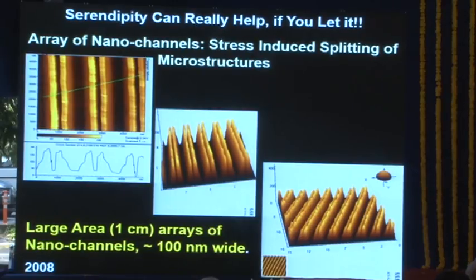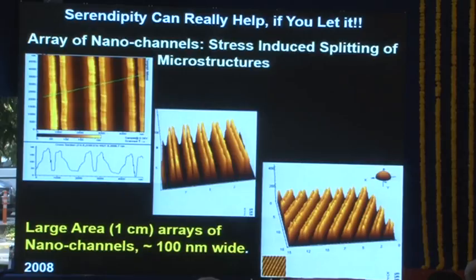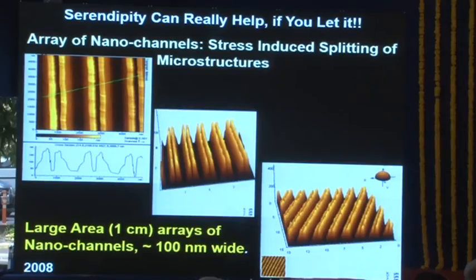Now, this happens because when you stamp on polymer, you create a sharp corner. There are a lot of stresses at that sharp corner. So they relax by forming a crack, which is quite predictable. And that crack goes down to the base of the triangle, and it makes a nano channel. Now, if you wanted to make the same nano channel by what are called top-down methods, like focused ion beam, those kinds of things, it would not be easy. It would take many hours of work. It requires a few million dollars worth of equipment and a lot of patience. But in this case, you can make it very easily. And of course, these nano channels can be used for many practical purposes.